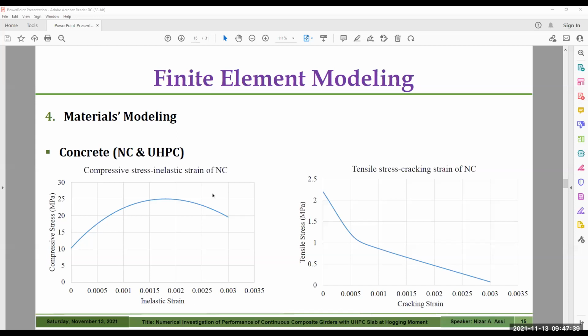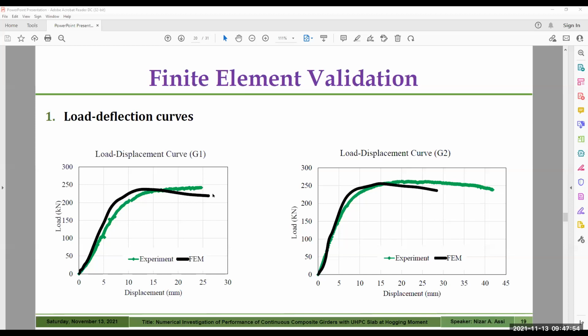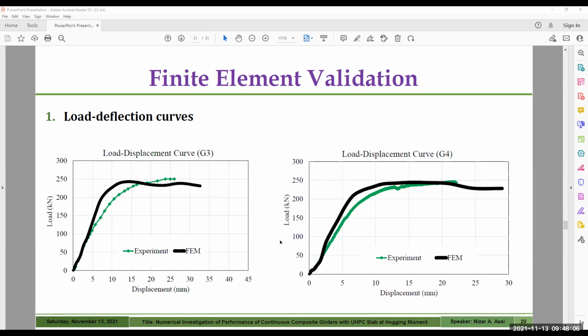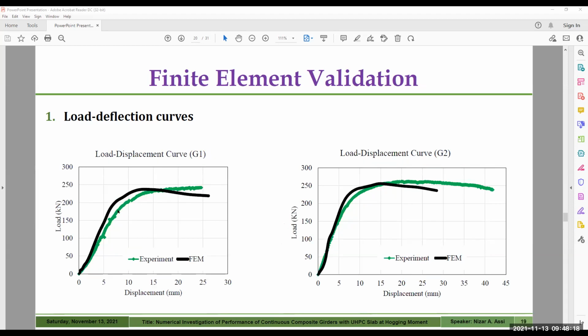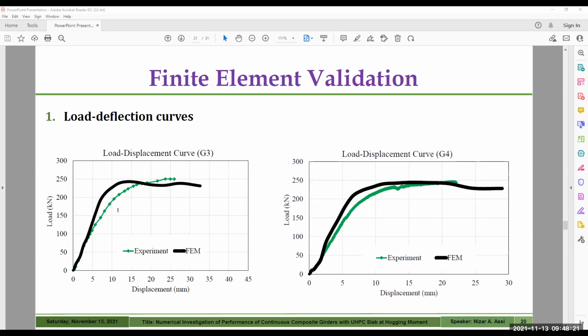Now I will talk about the validation of the finite element model. The validation was made through different stages. The first stage used the load deflection curves, which were obtained experimentally. As you see for G1 and G2, and here we have load displacement curves for the other two girders with different shear connections and different thicknesses of the UHPC slab. The comparison shows good agreement between the finite element model and the experimental results in terms of load deflection curves.